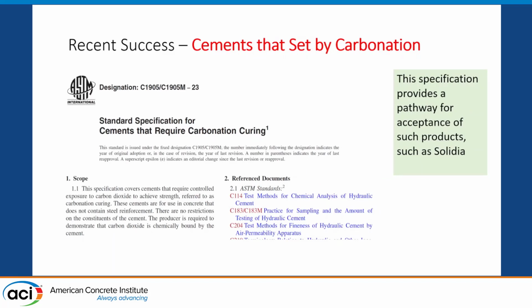There's a brand new standard that just came out in the last couple of months, for cements that set by carbonation. Some of these materials don't hydrate; they set by carbonation, so they sequester carbon. There are a couple of companies out there, such as Solidia, that use a wollastonite type of calcium silicate that binds with CO2. It doesn't harden on its own. It hardens with the presence of CO2. And there are some other companies taking advantage of that too.